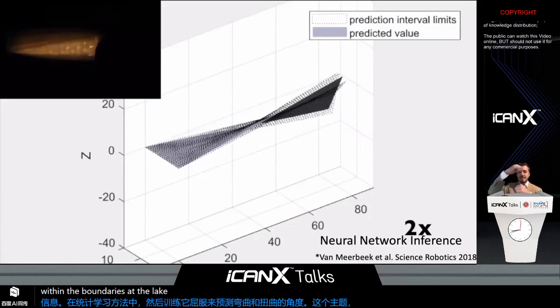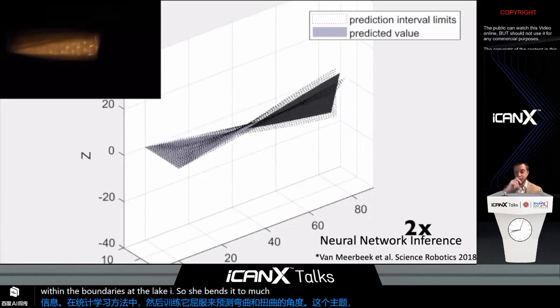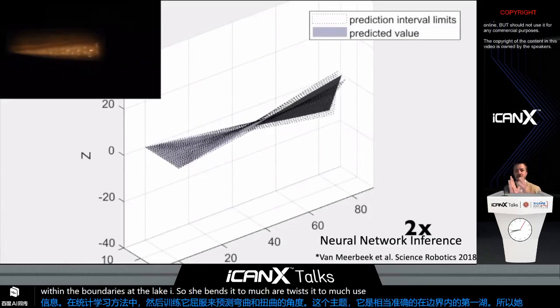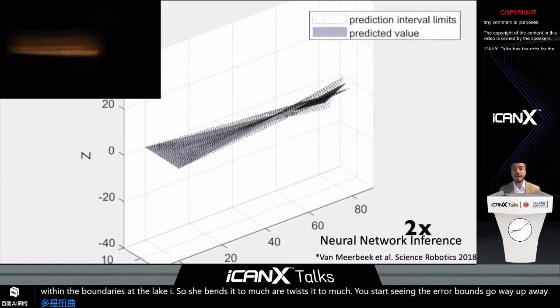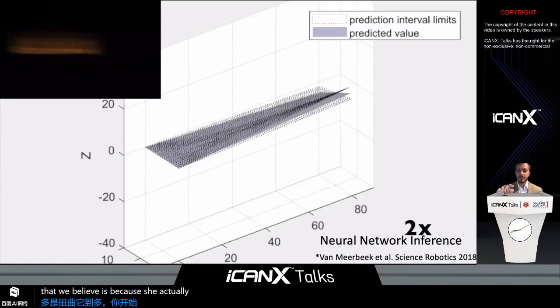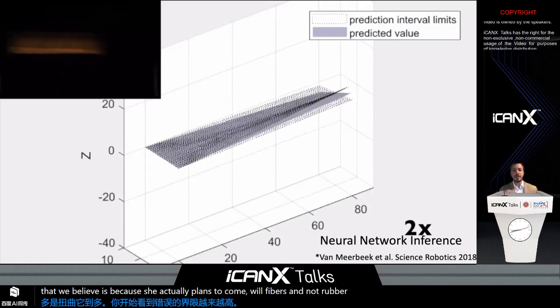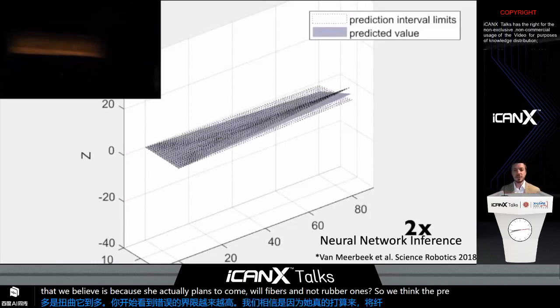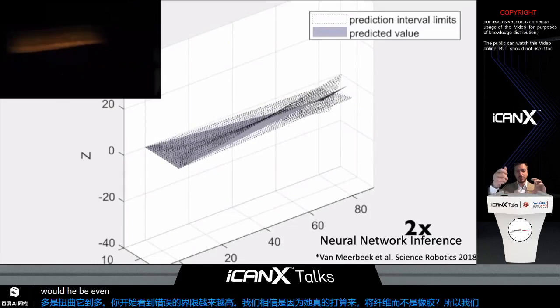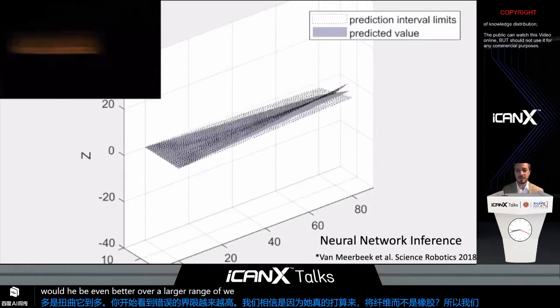So if she bends it too much or twists it too much, you start seeing the error bounds go way up. And that, we believe, is because she actually used plastic optical fibers and not rubber ones. So we think the predicted twists and bends would be even better over a larger range if we use soft light guides instead.